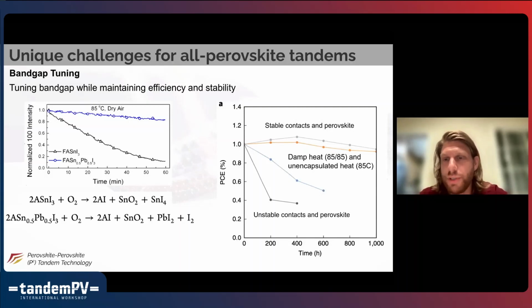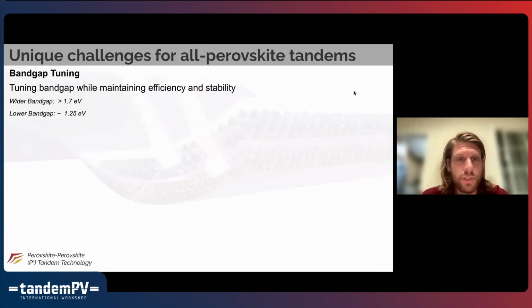can be extremely stable. And so we have this data that was published in Nature Energy a few years ago as well, where you can actually take unencapsulated low band gap solar cells and have them in an oven at 85 degrees for 1,000 hours and not see any significant drop in performance. And you can also do damp heat testing with encapsulated ones and not see any drops in performance.